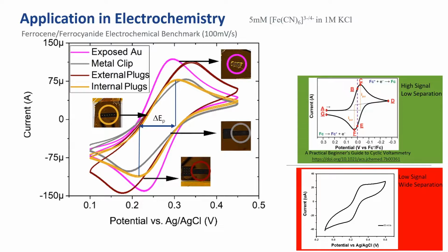Returning to the impact of contact resistance, in the voltammograms we see here that the exposed gold plot has a separation of 69 millivolts, close to the ideal value. We also show two uses of the contact plugs, one within the O-ring defining the active electrochemical area, and the other external to it. The internal plugs have a lower separation, but lower signal intensity, while the external plugs have a higher signal but a larger separation. The peak separation decreases with the decreasing access resistance, reducing the overpotential required to achieve the redox process, while the attenuated signal indicates that the inclusion of the contact plugs in the active area reduces the area available to carry out the redox process.